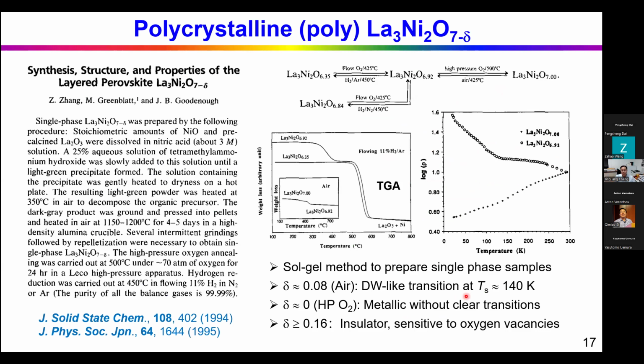Actually, this bilayer nickelate 327 phase is a pretty old compound that has been known since the 1980s. But according to the literature, it was not easy to prepare a single phase sample. In 1994, according to this paper by Professor John Goodenough's group, which is probably the first I can find, they reported preparing the single phase 327 phase by using the wet chemistry sol-gel method.